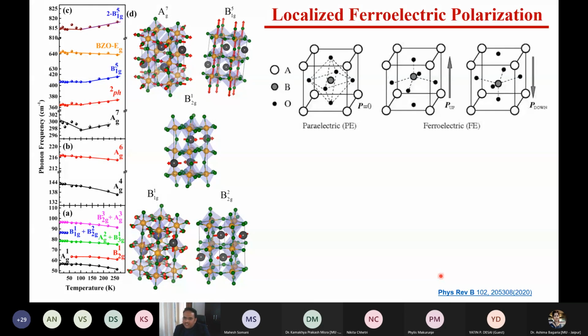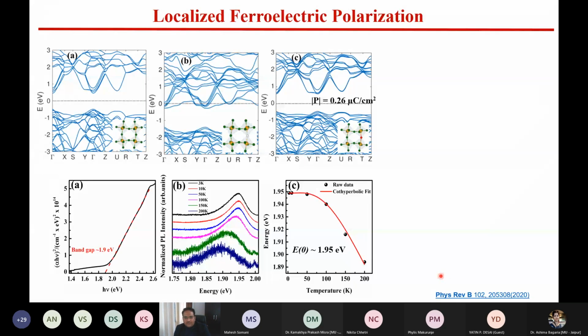Now, once you have ferroelectricity, that means you have a finite polarization. That polarization will help the electrons and holes to be separated from each other and keep them in the material for a longer duration. And this is where we try to understand how this distortion helps. Now, these materials have been grown from the oxide material. So what you do is you sulfurize the barium zirconium oxide at a certain temperature in the presence of sulfur. So you have some impurity oxygen.